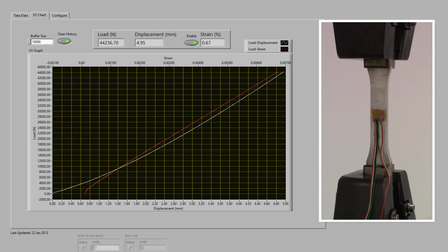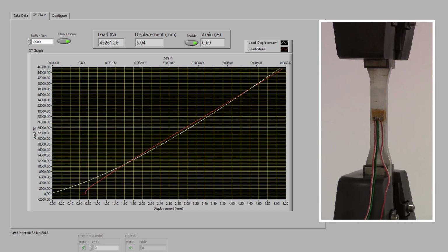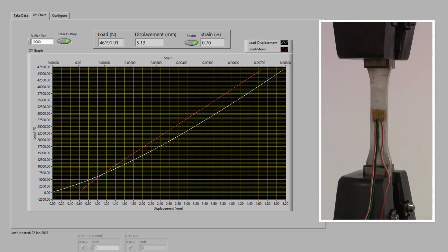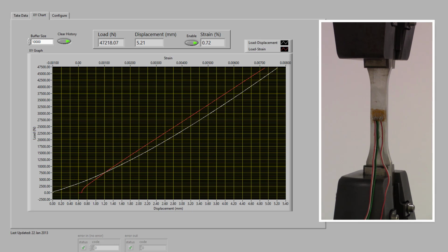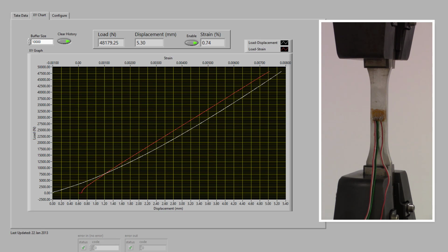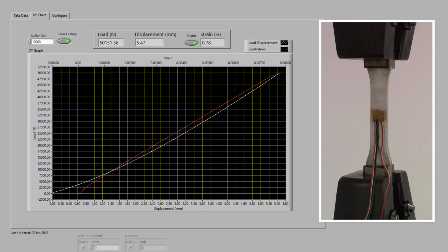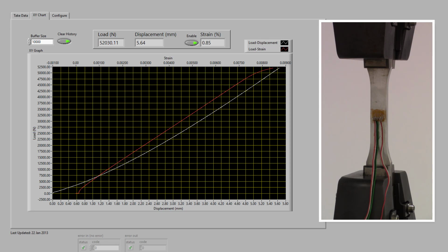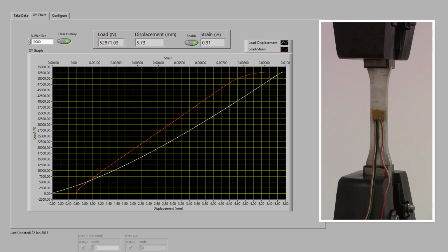Looking at the strain versus load plot in red, the straight linear curve indicates the specimen is currently in the elastic region. At around 50 kilonewtons, notice the knee in the curve, or the inflection point, as the specimen transitions into the plastic deformation region.